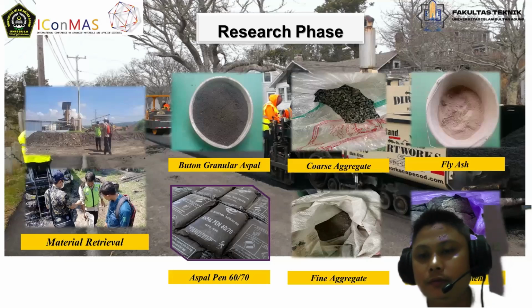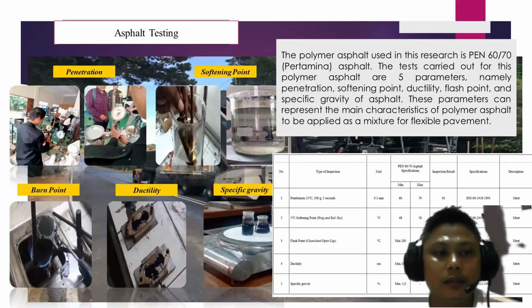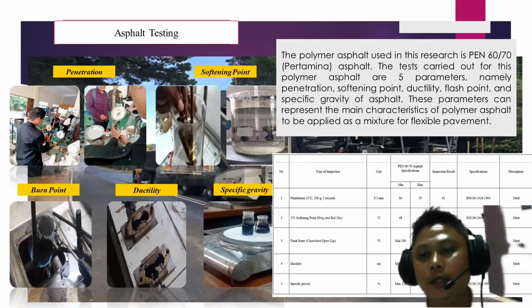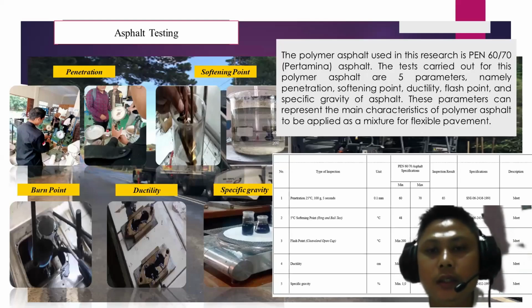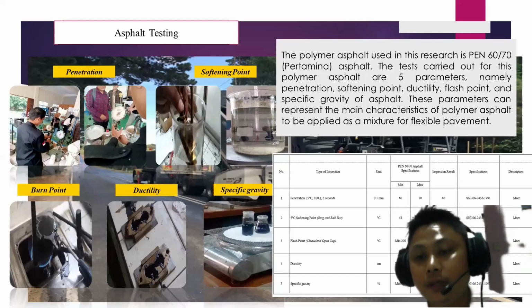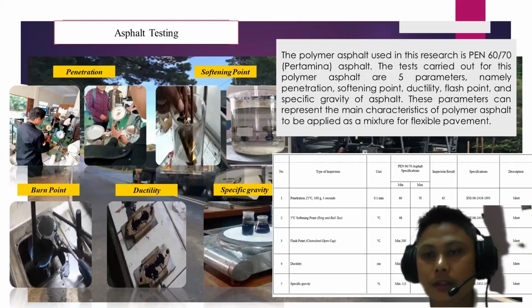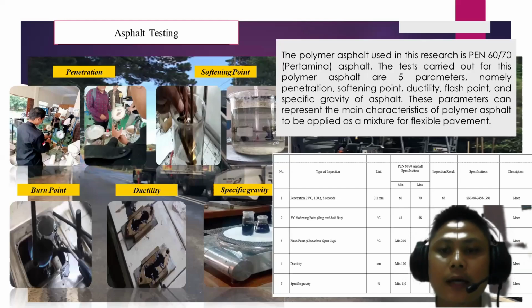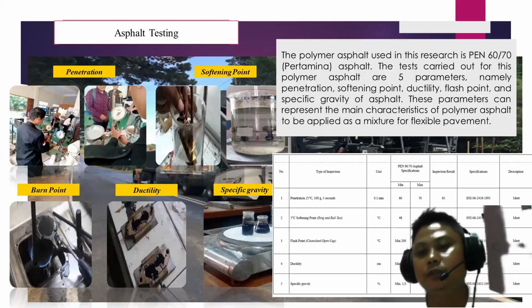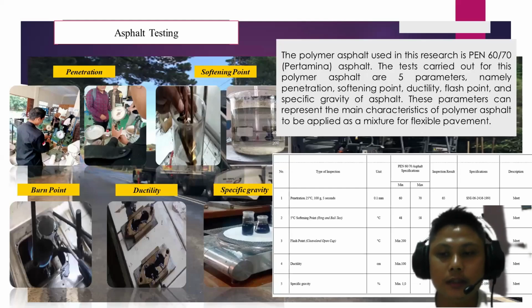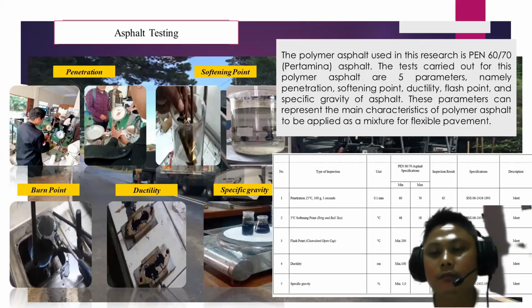This is the picture where we can find some material about the asphalt and asphalt testing. What is the asphalt testing? We can find the asphalt testing of the polymer asphalt from the research, and the tests carried out for this polymer asphalt are the five parameters: penetration, softening point, ductility, flash point and specific gravity for the asphalt. The experiment represents the main character of the polymer asphalt to apply to a mixture. What is the additive for this test? What is the result for this test?